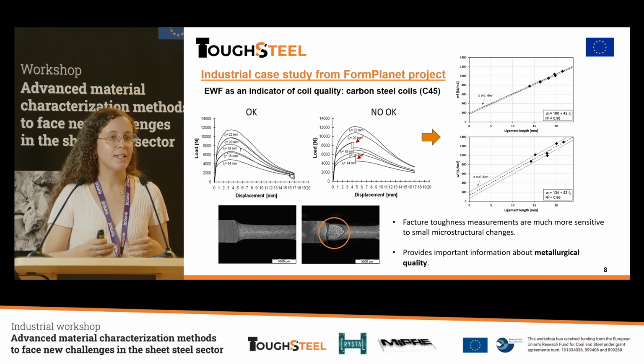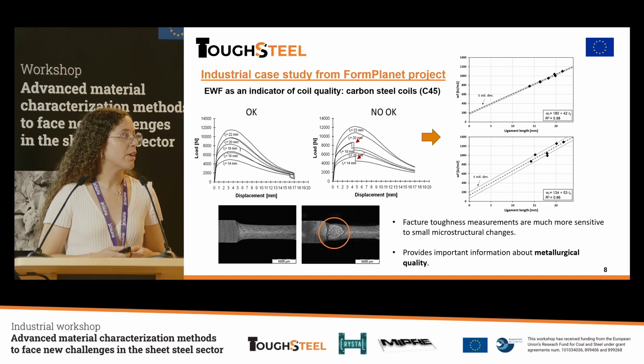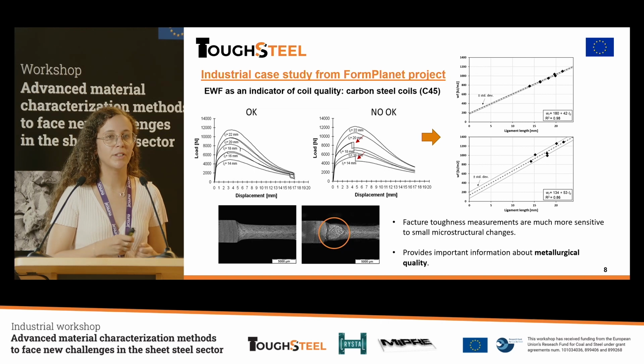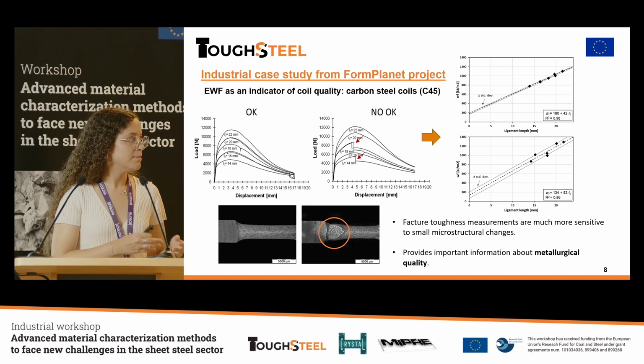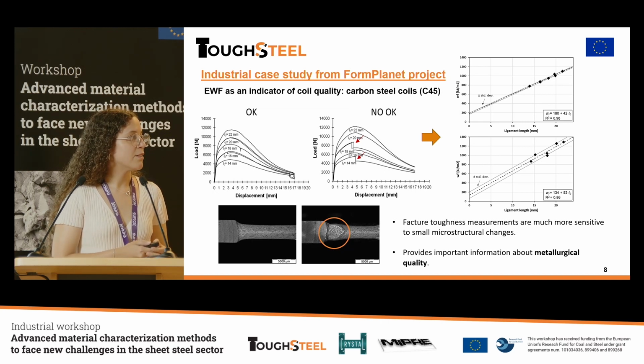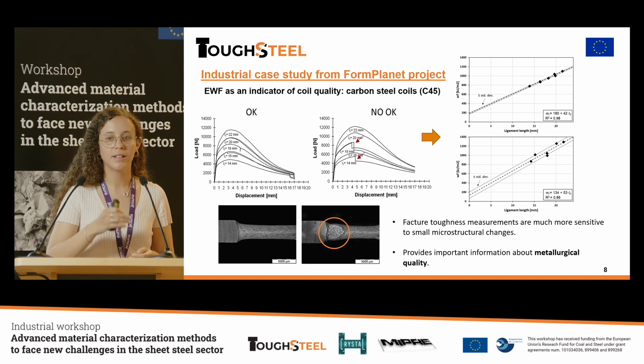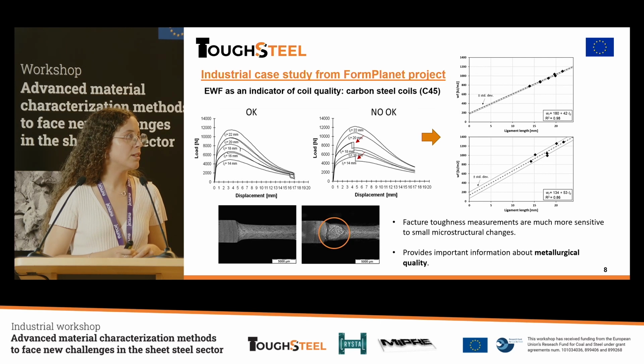When we performed the test, we could find that in the load displacement curve, when testing the specimens, we could already see some difference in the behavior of the testing part. We can see here in the red arrows that for this material we were finding some drops in the load during the tensile test.